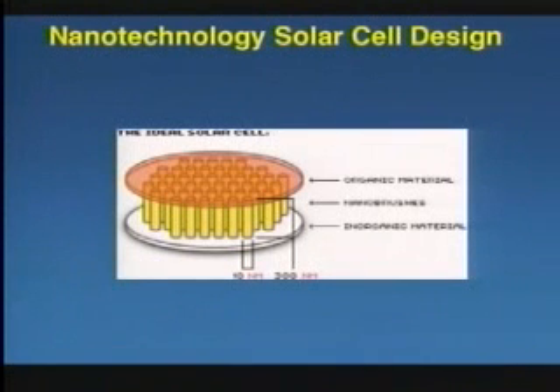But nanotechnology can change that because, in fact, here's a design that on paper looks like it will fit that criterion. Suppose this is silicon and it's 100 microns thick. I don't have to make 100 micron diffusion length silicon if these are nanometer diameter rods that I have current collectors to collect them on, because now I can collect them laterally, and the diffusion length can only be a nanometer or 10 nanometers, even though I can have the full absorption length normal to the surface. We've actually done, with Harry Atwater and my group, a full analytical device physics model of how these will perform as a function of lifetime, surface recombination velocity and doping. And so we are pretty confident we know what we have to make.